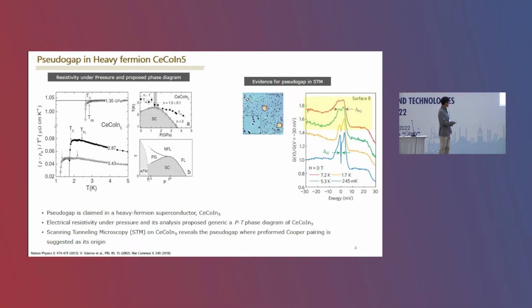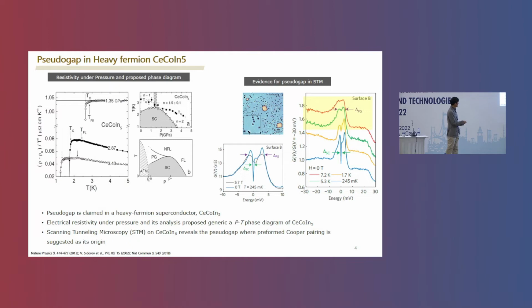And then when a magnetic field was applied, they found that this superconducting gap feature was completely suppressed. However, the pseudogap-like feature still survives.